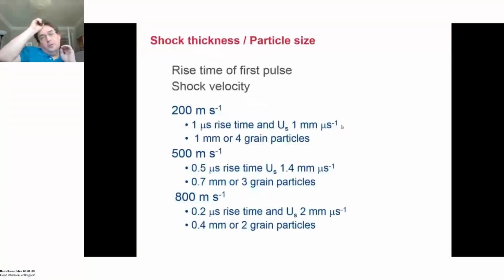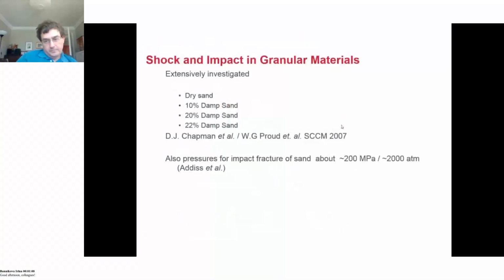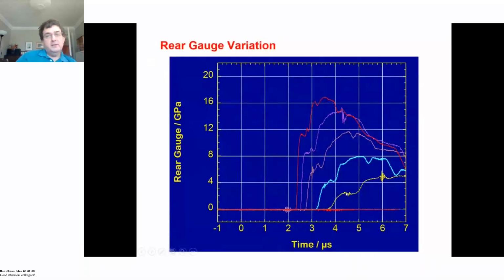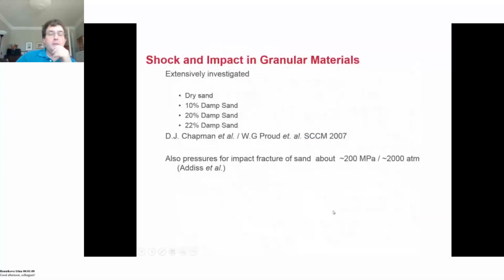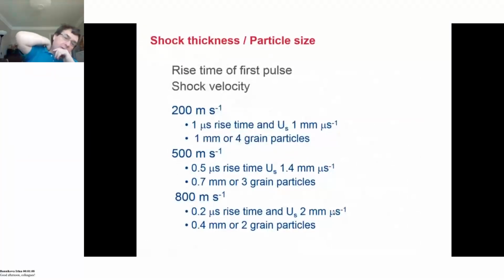Okay, now one calculation you can do is to think about what's happening in the grain size response compared to the global shock response. So what is the rise time of that first pulse through the system compared to the size of the particles? Under 200 meters a second, you can compare the 1 microsecond rise time against a shock speed of around 1 kilometer per second. And what this means is that rise time represents a size of 1 millimeter, or 4 grain particles.